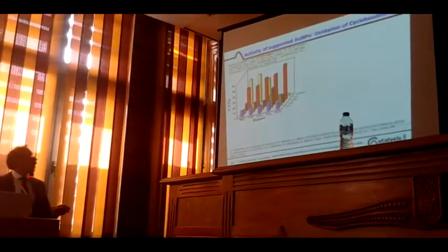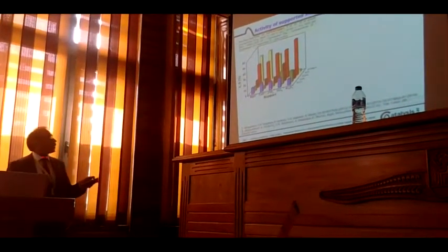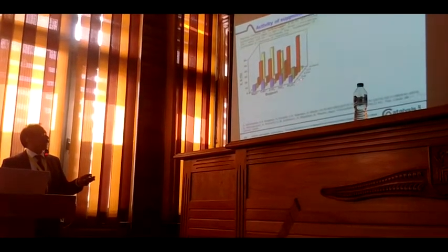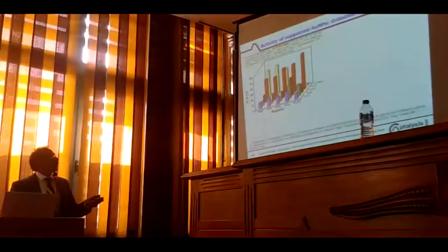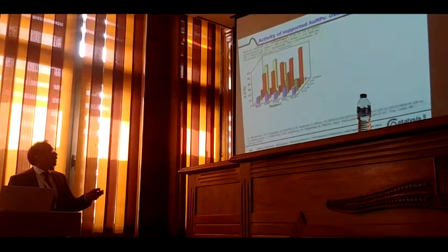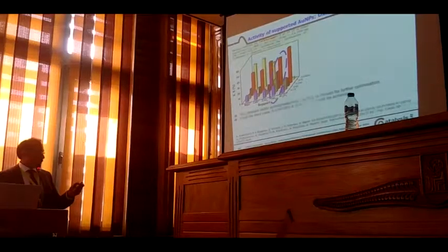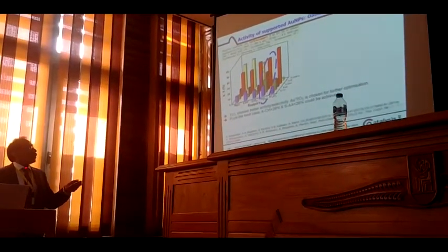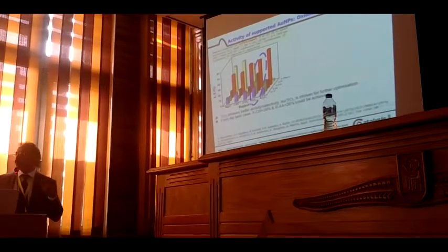So this is the activity. This figure looks somewhat complex, I'm sorry for that, but just consider the first 2 rows. The first blue one is conversion of cyclohexane, X_CH, CH is cyclohexane. And the second row, green one, is selectivity of adipic acid. If you look at this among different supports, titanium has shown relatively good performance. And other products are again cyclohexanol and cyclohexanone, which we are not able to prevent.